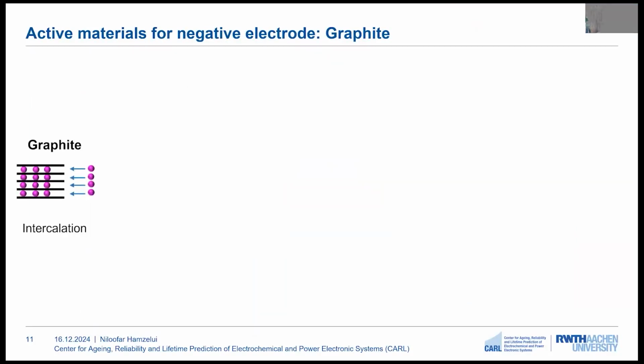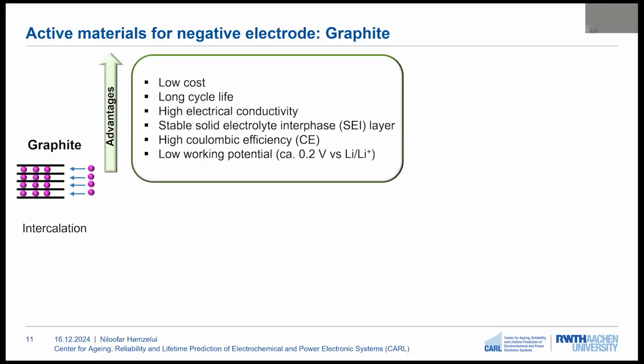So what kind of active materials are being used in the negative electrodes? The most commonly used active material is graphite, as it is schematically shown here. We are seeing the graphite layers, and during lithiation and delithiation, the lithium ions can intercalate and deintercalate in between the layers. The benefits of graphite are that it has a low cost, it has a long cycle life, it shows a high coulombic efficiency, a stable solid electrolyte interface, and it has a low working potential.